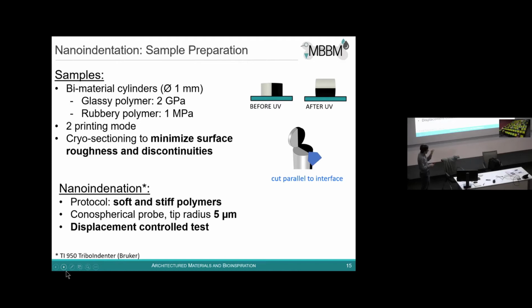So we pressed a diamond tip on the samples and measured the force and the displacement of this tip. And then we used models, based on the force-displacement curve, to get the local Young's modulus, basically. And this is also a little bit tricky, not straightforward, because we have to indent in stiff polymer and in soft polymers. And in soft polymers, you have adhesion effects. This is something that you have to take into account when you indent in these.